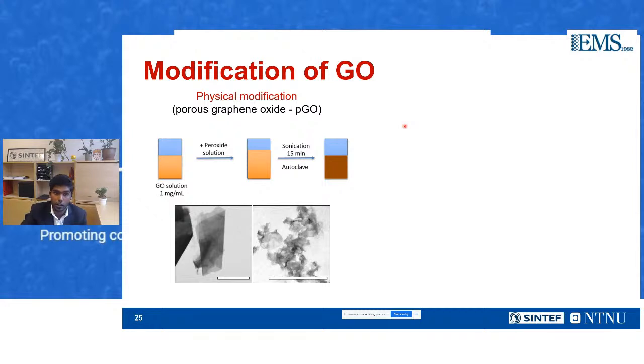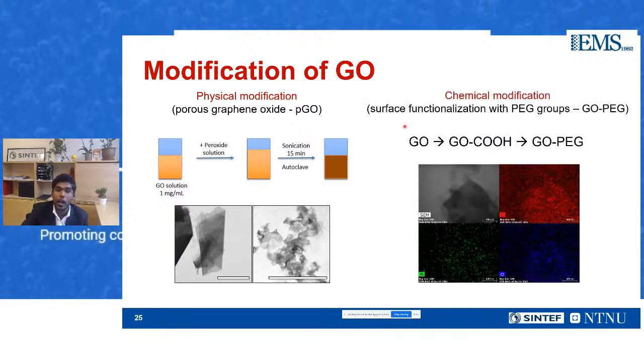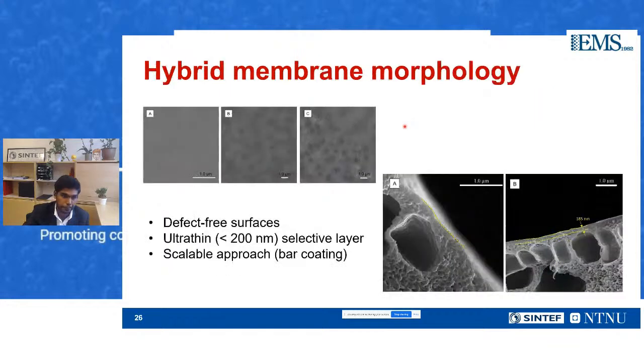One is physical modification, where you have porous graphene oxide, which includes a large number of unselective pores in the two-dimensional matrix across the plane of the graphene oxide. The other is chemical modification, where we include PEG functional groups, because we saw the success story from the nanocellulose, and we want to functionalize the graphene oxide with PEG to make it more hydrophilic. We were able to make these two nanofillers and disperse them in the same facilitated transport matrix, which is sterically hindered polyamine. And then we eventually